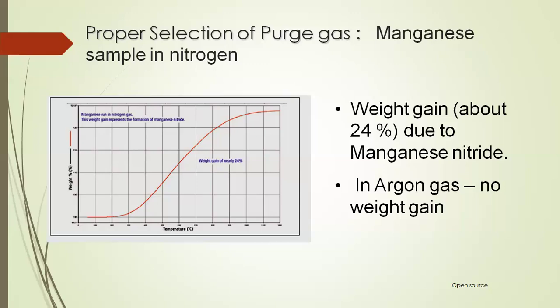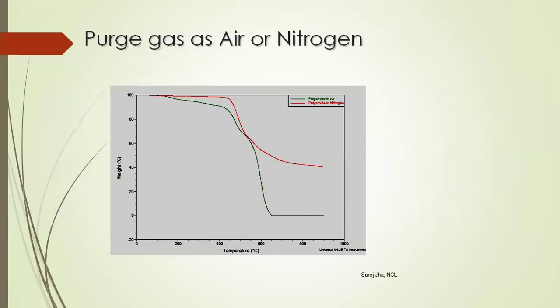And remember, when you change the purge gas, just take a baseline in the changed purge gas and see what is happening to the sample holder, and then run the sample in the different purge gas. So for manganese, not air, not nitrogen, but argon is the right purge gas, an inert atmosphere. So you should know a little bit about your sample also. And if you don't know anything about your sample, it is an unknown sample, for polymer people, do it in nitrogen and do it in air also, and see if you are getting a difference in the degradation process.